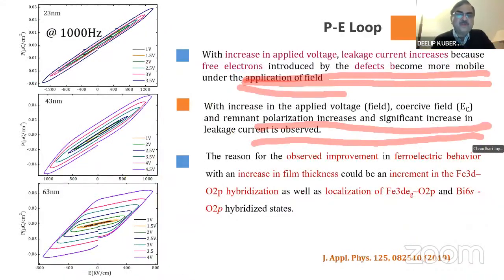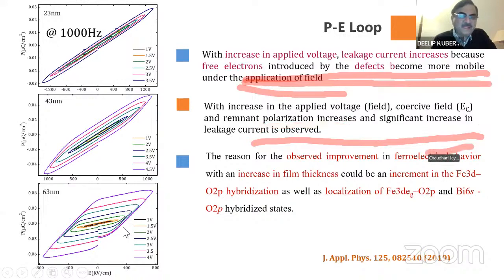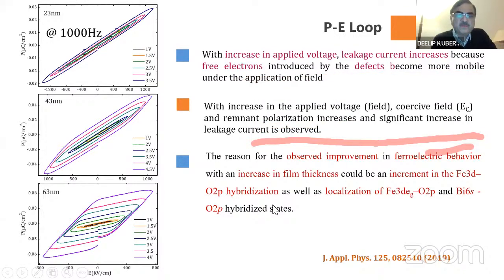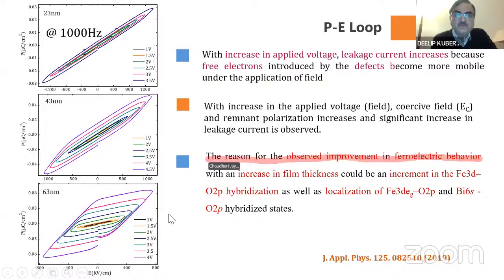So this is the P-E loop. In the 63 nanometer films, at least, you can get a good P-E loop and an observed improvement in the electrical behavior. Otherwise this is not a good loop. In the low thickness films, 23 and 43 nanometer, you don't get good saturation of the polarization, but you get a proper or acceptable loop when the thickness is larger.